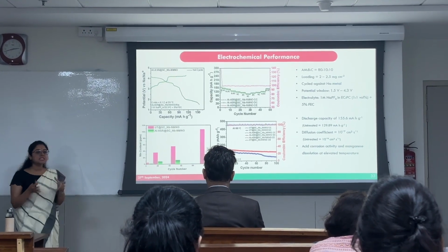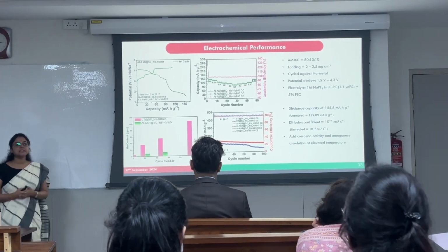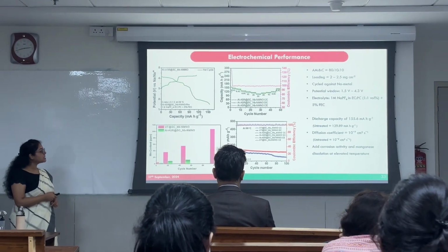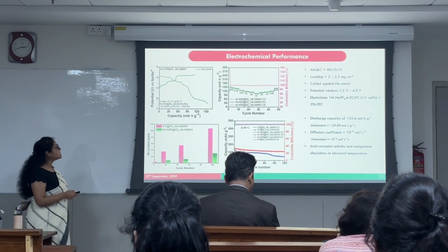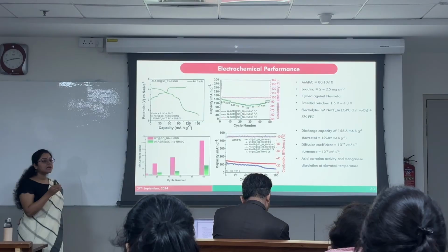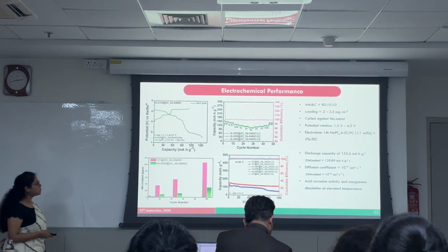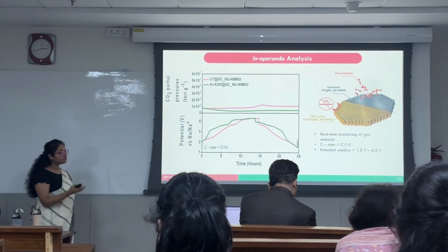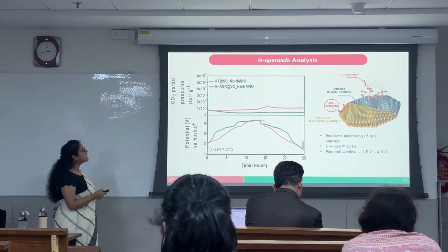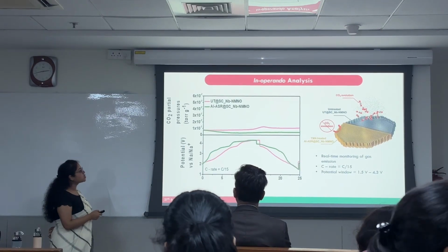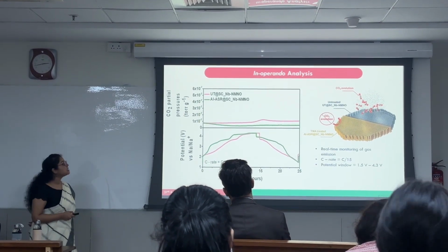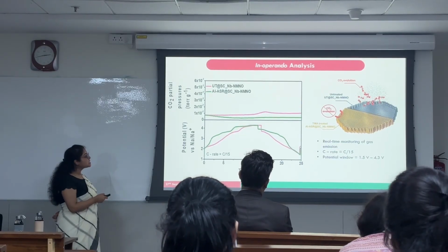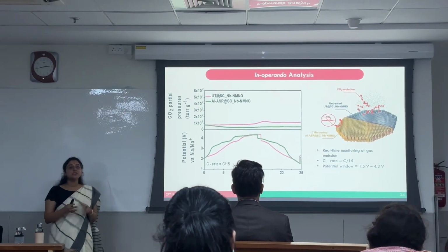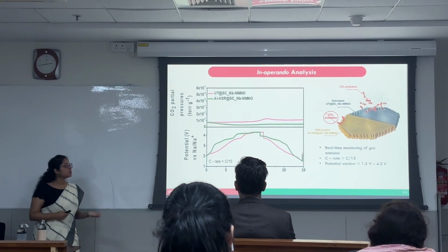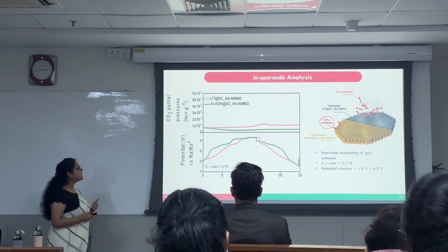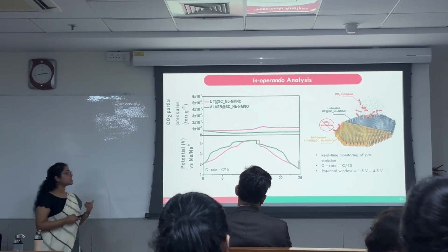And finally, to see whether there is manganese dissolution taking place, we conducted the ICP analysis of the separator and observed that the manganese content in the separator after cycling in the untreated sample is much more in comparison to that of the treated one. We then found out that the CO2 evolution after coating has become minimized when we monitored it through the online electrochemical mass spectroscopy, and it is almost zero. So this tells us that indeed the coating has been advantageous for the problem of manganese dissolution.